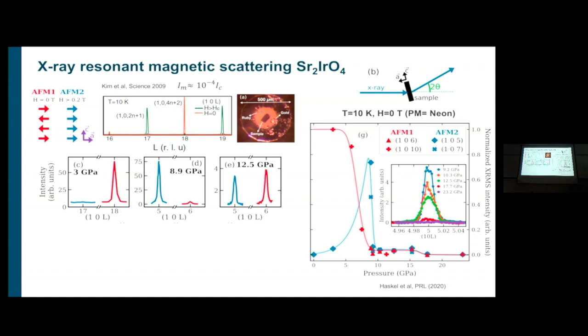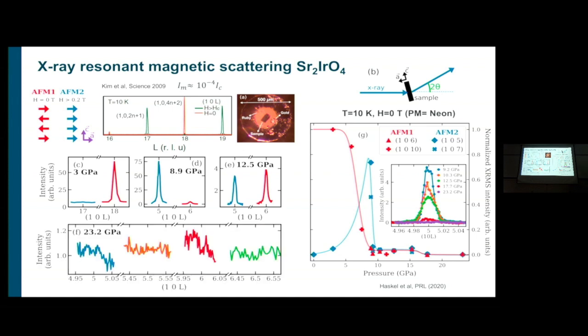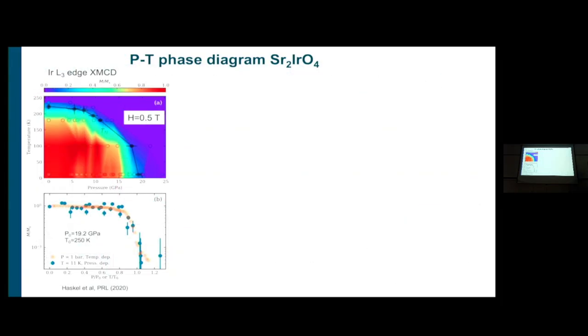And if you keep going and you go to the 20 GPa, remember the hysteresis loop collapses. Here the magnetic signal also disappears. So we no longer see it goes here, it switches, and then there's something weak, and then it goes away. So both XMCD sees that the magnetization goes away. Resonant magnetic scattering sees that the magnetization goes away. There is no magnetic order. We look for other magnetic peaks. We don't see any.